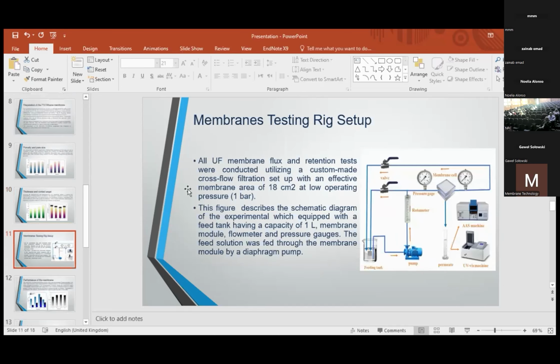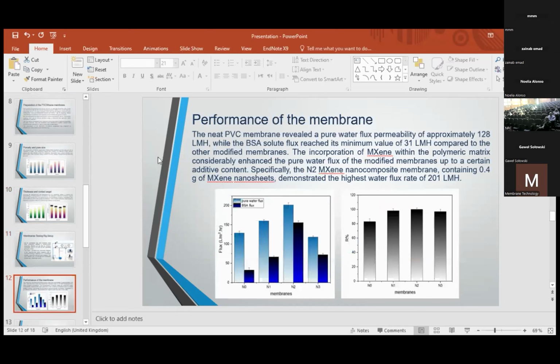For testing performance of membrane, we utilize a custom-made cross-flow filtration setup. This figure describes the schematic diagram of the experimental work. The neat PVC membrane achieved a pure water flux permeability of approximately 128 liter per meter squared per hour, while the BSA solute flux reached its minimum value of 31.